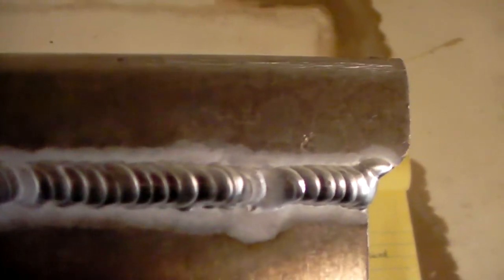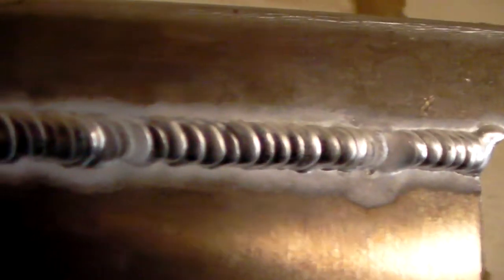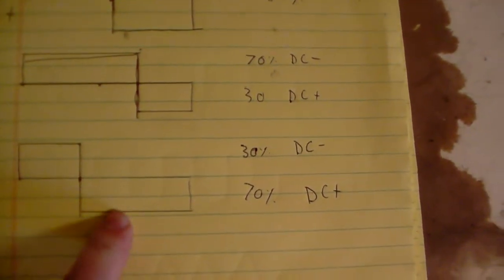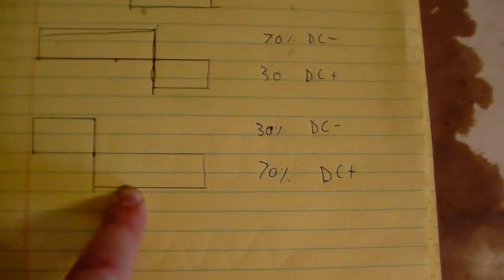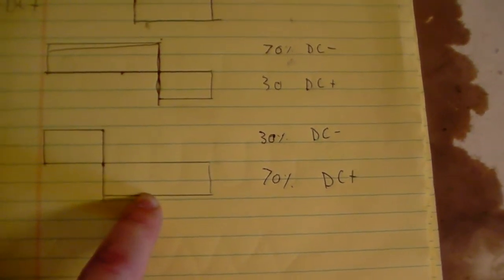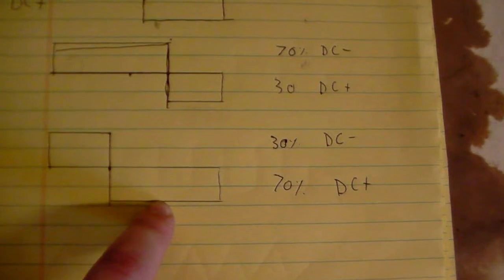You'll notice on this one, you see that white line right onto the edges of the weld that run all the way across? That is what's called an etching line. That is what the positive side of your arc is doing. It's moving all the oxides out of the way so that you can weld to the aluminum underneath it. So, that is why you want balance. Now, this one is more like if you're welding really dirty aluminum that you got to move a lot more stuff out of the way of, so that you can get down to your aluminum.